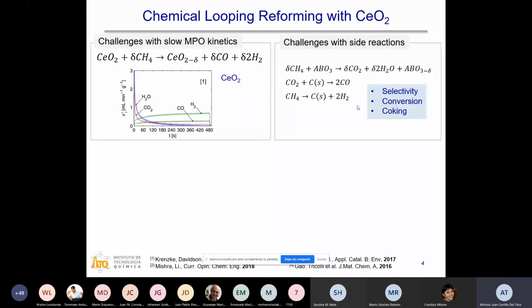I'm showing here a plot that represents the production versus time for this reaction. At the top, the production of hydrogen and carbon monoxide is quite flat. It's not a fast process. There are also challenges with side reactions because methane can combust with the oxygen at the surface of the oxide, and produces water and CO2, as observed also in this graph at the very beginning of the reaction. Methane can also crack and form hydrogen and carbon depositions, which affects the hydrogen to CO ratio. These carbon depositions, if we do CO2 splitting on the next step, will be transformed into carbon monoxide, so we can somehow get rid of it.